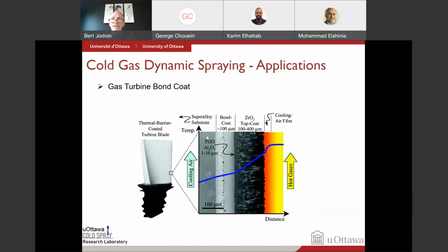And on top of it, the ceramic layer lets oxygen go through. So the oxygen can go through and attack your base material. So this bond coat also serves as a barrier to prevent oxygen from attacking your base material by forming a tiny layer called a TGO, thermally grown oxide layer, an alumina layer that grows out of your bond coat that prevents the oxygen diffusion.